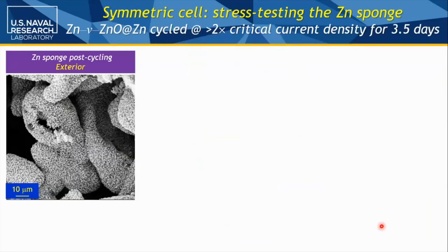So we first wanted to stress test the performance of the sponge, just as you would for a lithium system, to see when dendrites form under which electrolyte and which loads. And it's known for zinc in alkaline that it's sort of in the ballpark of, you know, pick a number, 6 milliamps per square centimeter, which in the old days, you typically weren't trying to push your battery toward.